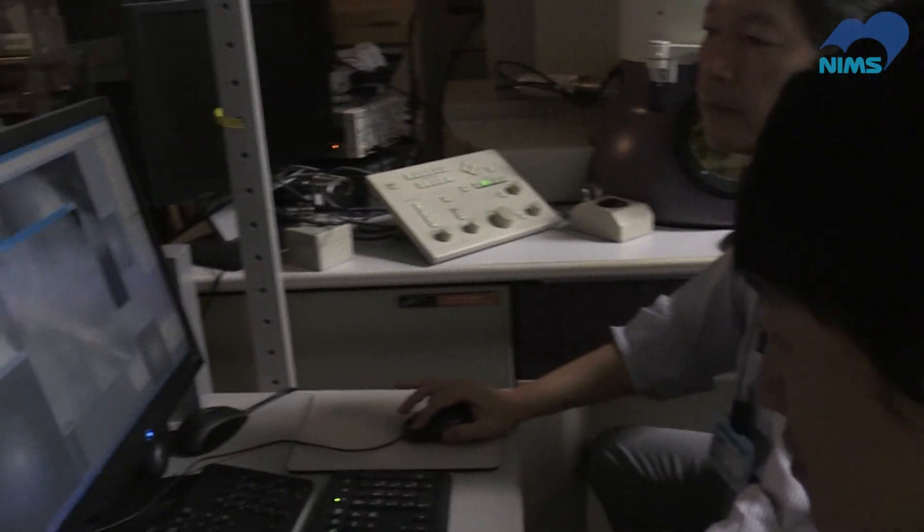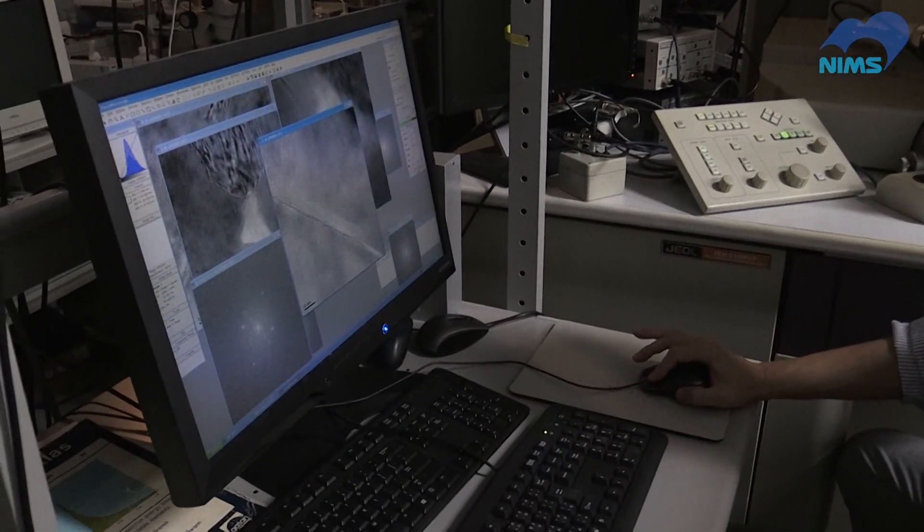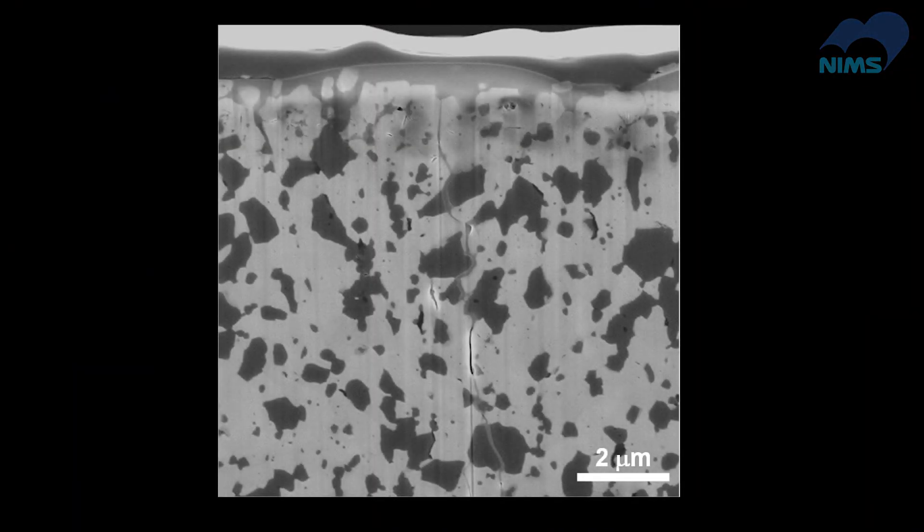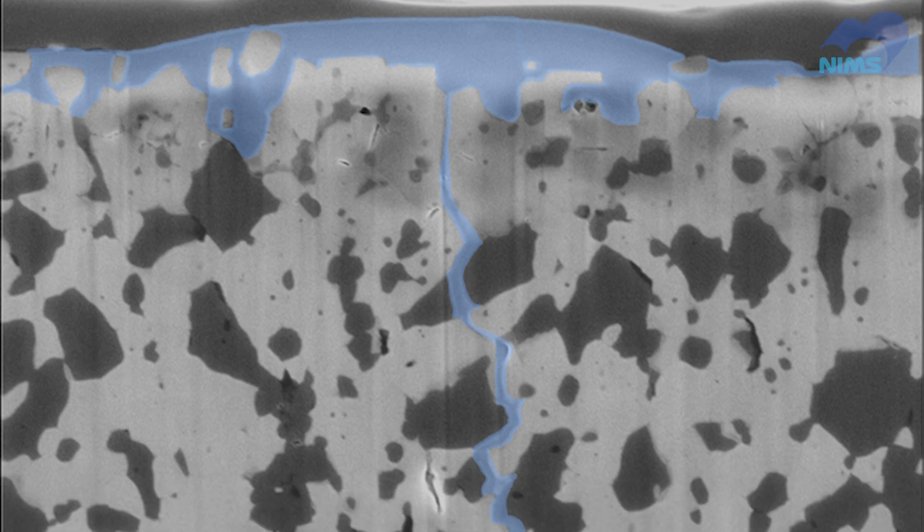He began a detailed investigation of the self-healing process with state-of-the-art analytical instruments at NIMS. Finally, he succeeded in taking a very interesting photograph. He discovered that a liquid-like substance was filling the cracks. It turns out that this liquid filling of the cracks is the first stage of the healing process.